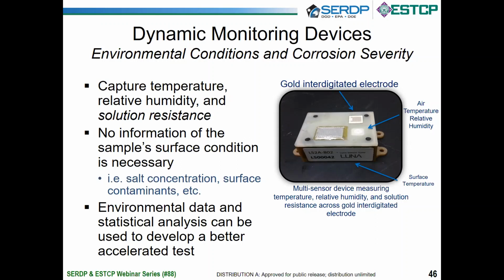environment. So what we've done so far is to deploy these sensors with mass loss coupons, aluminum and steel coupons, to measure the temperature and humidity, sometimes hour by hour. I think the lowest data recording limit is about every 5 minutes. And we do these for very long periods of time so that we can get a good idea about what exactly these mass loss coupons were exposed to in terms of temperature and humidity, and how we can correlate that mass loss to what we're seeing with the solution resistance measurements.